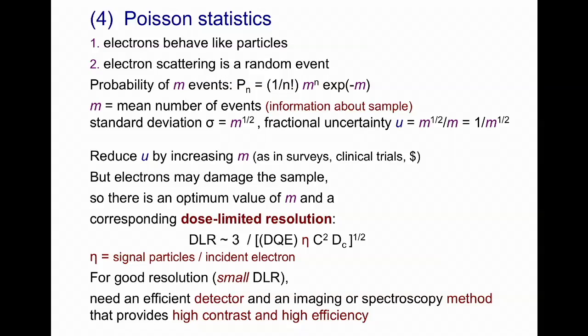If we use too many electrons to analyze a beam-sensitive specimen, they destroy the structure we are trying to measure because of radiation damage. So there is a maximum allowable electron dose, DC, that depends on the radiation sensitivity of the specimen, and the concept of dose-limited resolution takes this into account. The formula for DLR shows that it depends on the detective quantum efficiency of the electron detector and on the efficiency of our signal collection. It also helps if we have a specimen and an imaging or spectroscopy method that provides high contrast C between different regions of a specimen. That's why phase contrast is used for high-resolution imaging of organic specimens, and why a lot of effort has been put into increasing the collection efficiency of X-ray detectors.